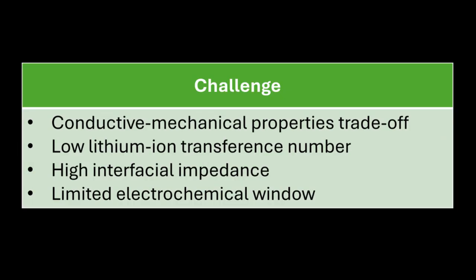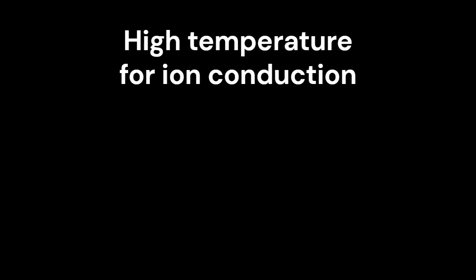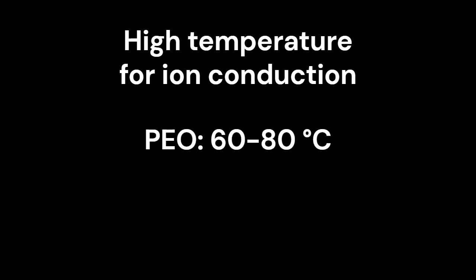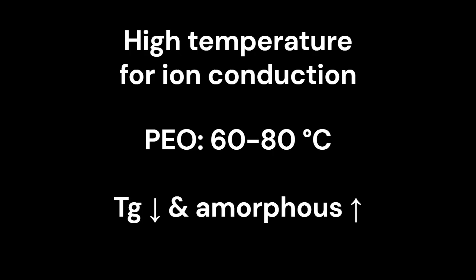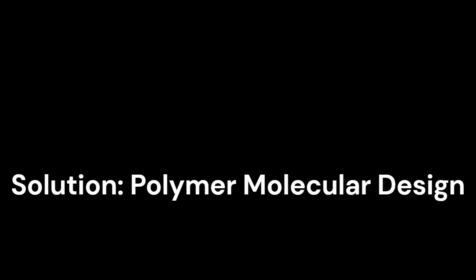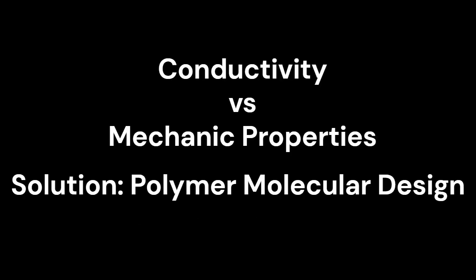Solid polymer electrolytes still face several challenges. Most require moderately elevated temperatures to achieve high ionic conductivity. For example, PEO-based electrolytes typically operate at 60 to 80 degrees Celsius. Improving room temperature conductivity usually involves increasing the amorphous content and lowering the glass transition temperature. But a lower glass transition temperature often weakens mechanical properties. Molecular design of polymers is one strategy to reduce this trade-off.